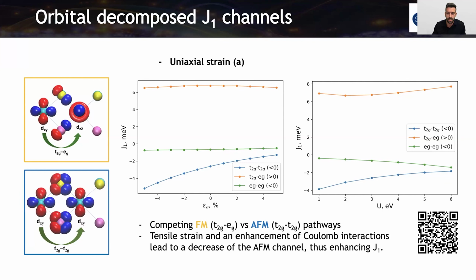In this case, for example, we have the sulfur and the bromide, and there's a chemical bond where there's electron density that is not perfectly ionic. We don't have exactly a chromium 3+. I'm sorry for interrupting, but ionicity has nothing to do with that. You are talking about distorting the octahedral environment, so the separation into t2g and eg manifolds is not exact. Is that what you mean? Yeah, that's the point.